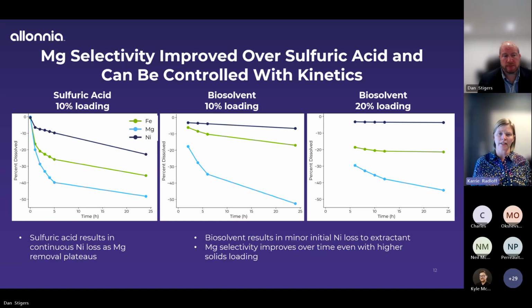Our biosolvents, on the other hand, have that nickel loss as a discrete first step, but then it really plateaus. It stays steady over time, particularly as we increase the amount of solids loading, while we get increasingly more of the magnesium and iron removed. So this tells us that we can do more with our biosolvent to improve that initial nickel loss, that's not really inherent to the magnesium and iron solubilization mechanism, and then really can drive the selectivity of the biosolvents.